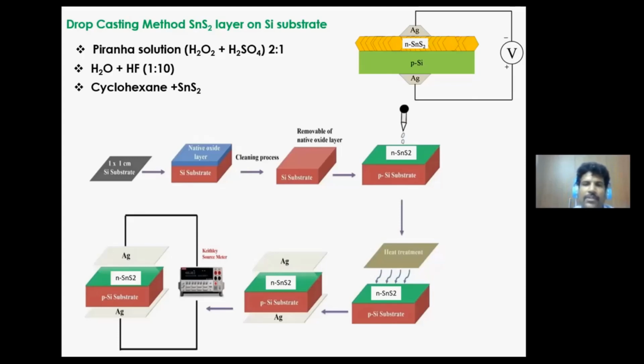We followed the same kind of coating for all three materials. We maintained the same ratio between cyclohexane and the particles. So we formed a layer. The heat treatment was done under vacuum, so we used a vacuum furnace for heat treatment.